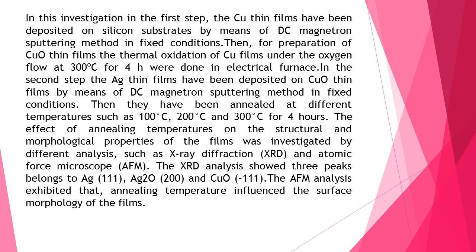In this investigation, in the first step, the Cu thin films have been deposited on silicon substrates by means of DC magnetron sputtering method in fixed conditions. Then, for preparation of CuO thin films, the thermal oxidation of Cu films under oxygen flow at 300 degrees Celsius for four hours was done in an electrical furnace.